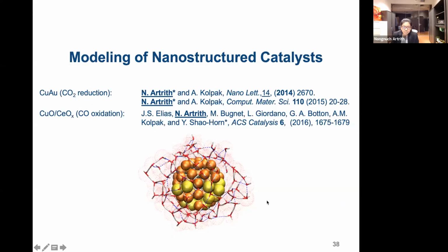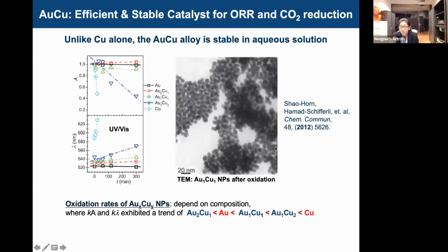Another example that I would like to briefly show you is how we model nanostructured catalyst systems. For example, copper gold nanoalloys are efficient and stable catalysts for the oxygen reduction reaction and also CO2 reduction. Copper itself is a good catalyst, but it oxidizes too fast in the reactors, like you can see here, only the light blue one, which stopped in the reactors in a really short time. But Professor Yang Shao-Horn, these are images from the Shao-Horn lab at MIT, demonstrated that mixing with gold helps the reaction stay longer and more stable.